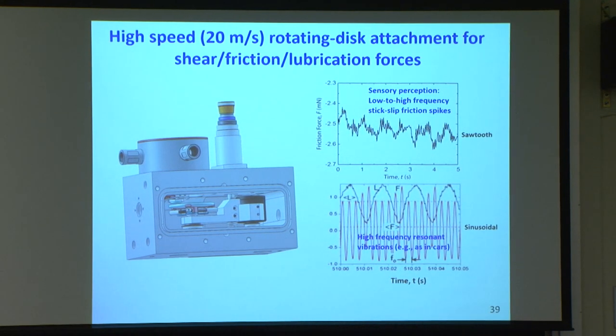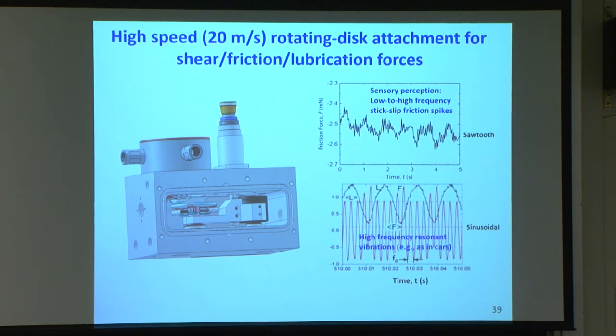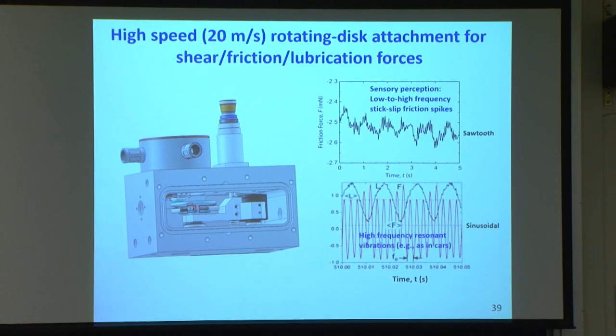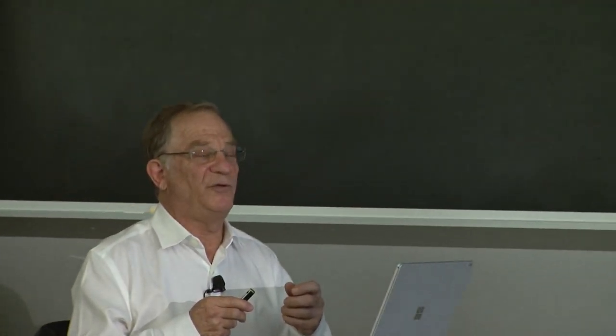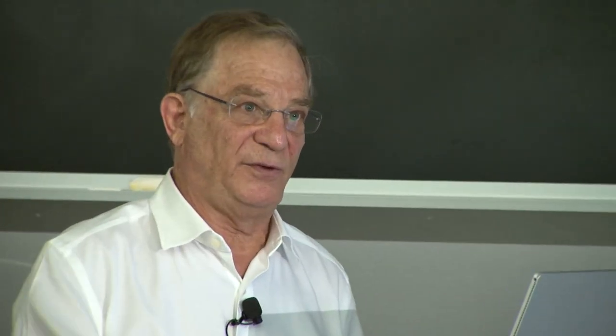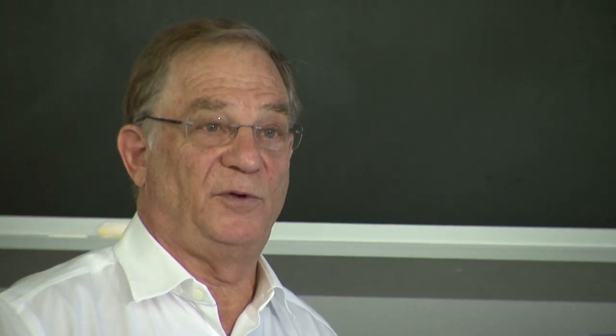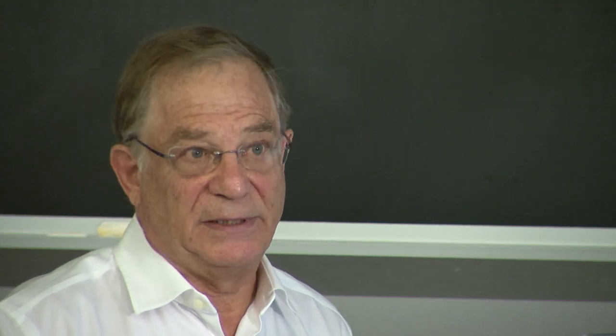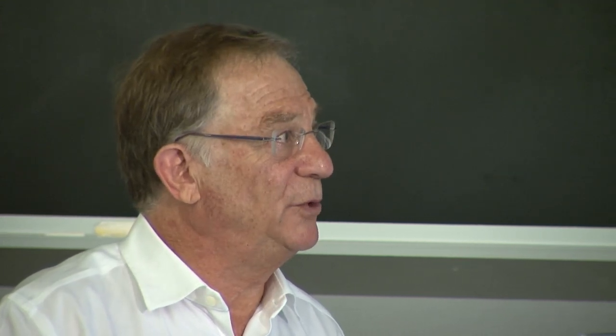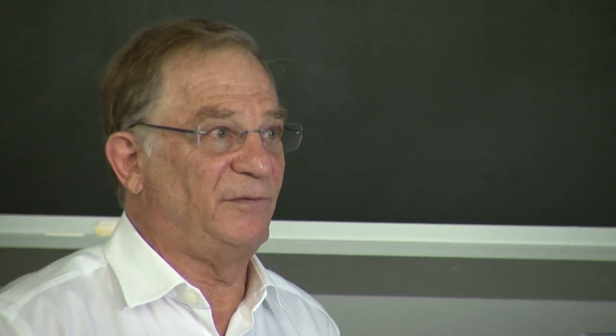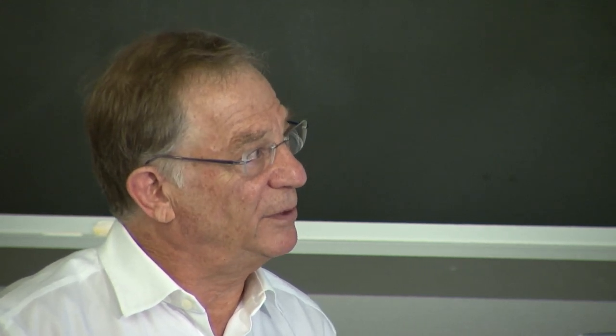Then it turns out you can go to a totally different frequency regime, and then you get sinusoidal things. And sinusoidal things usually mean it's not stick slip anymore due to surface friction. It's a mechanical vibration of the system that's causing you to stimulate one of the resonances of the system. And very often the two are confused. And so that's an interesting thing, especially in motor cars and so on. When you get these vibrations, when you engage the clutch or,